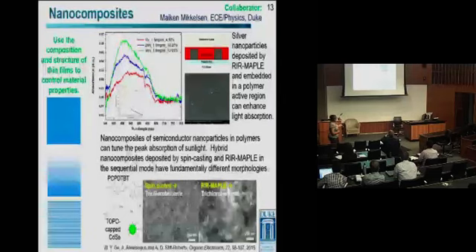And the main point is that you can see that the morphology is totally different. And this morphology is solvent dependent. So depending on the primary solvent, you can get different structures within that spin cast film, whereas the MAPLE film has a consistent morphology that's independent of the solvent and is much more dispersed in terms of the nanoparticles within the polymer. And so having that type of capability, also the ability to make a gradient profile.